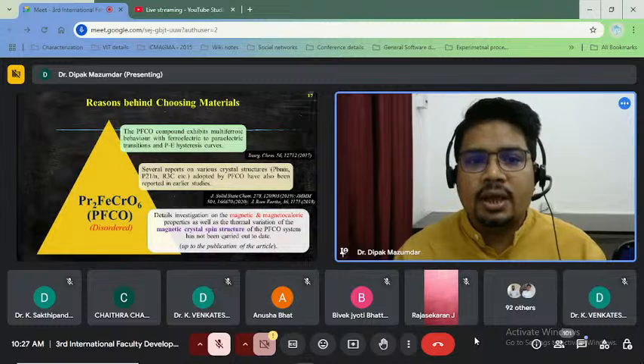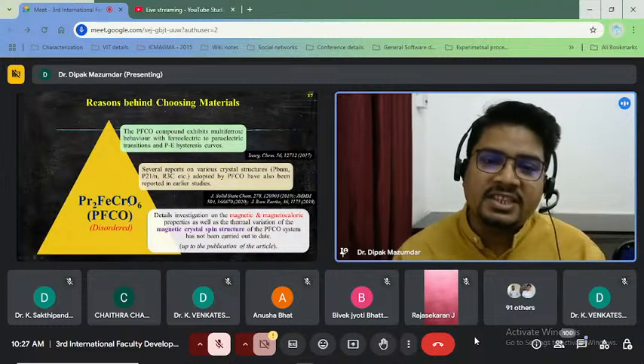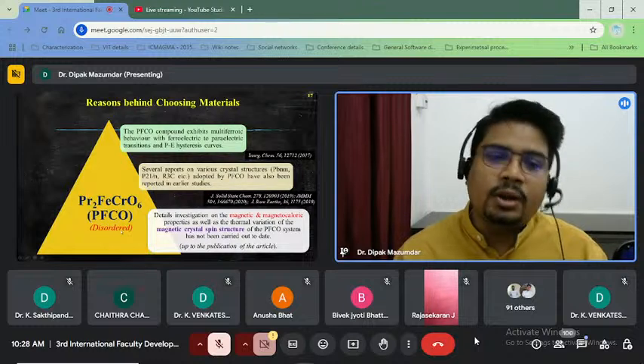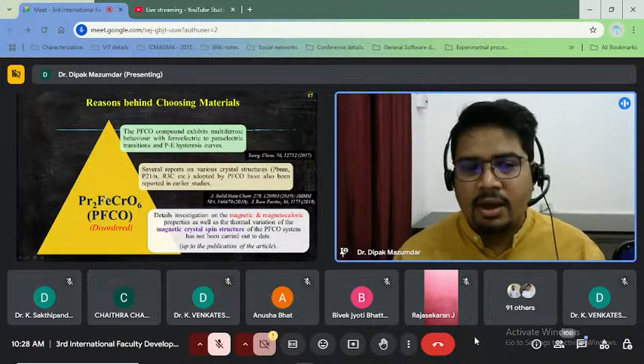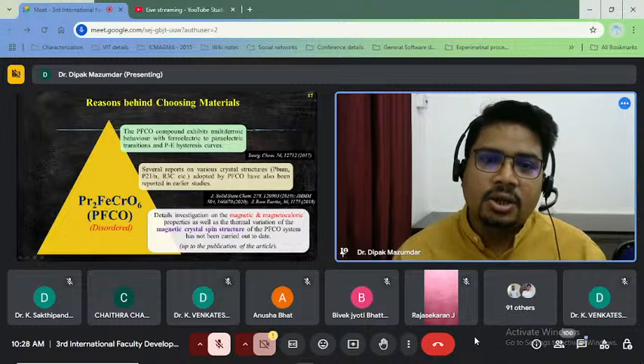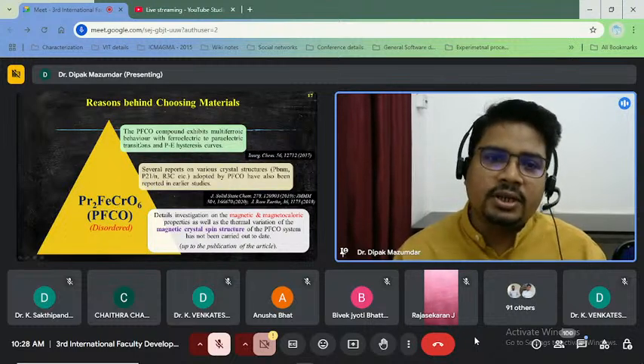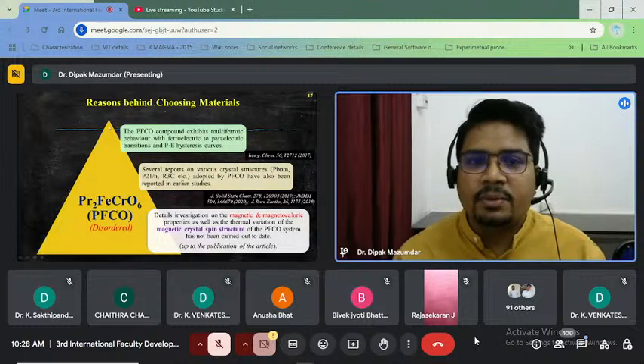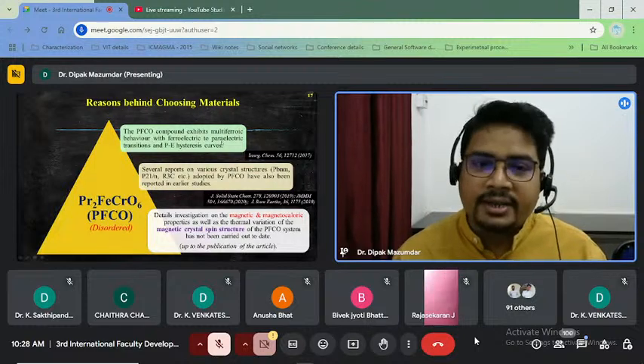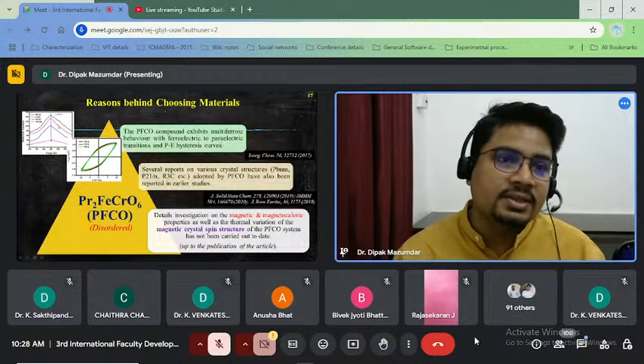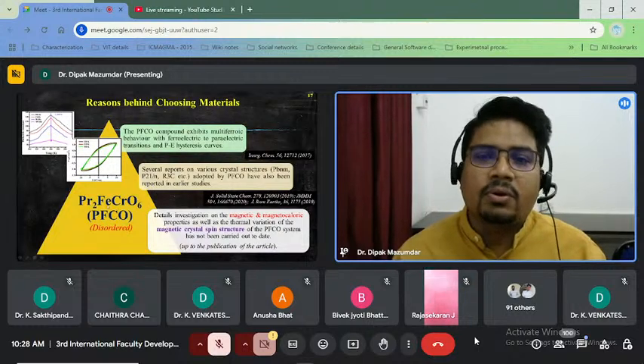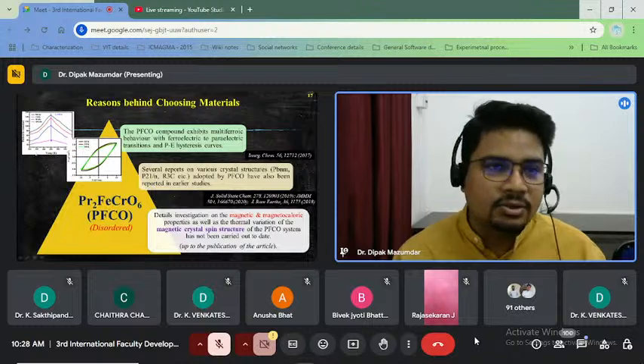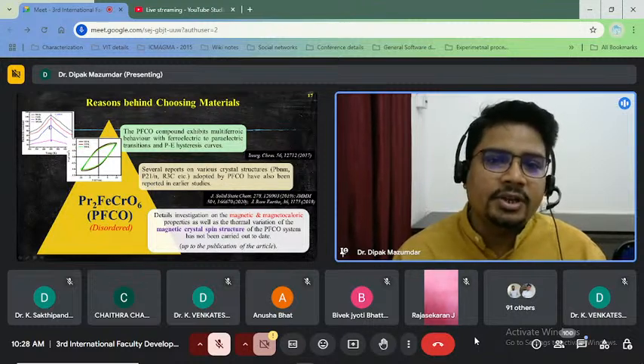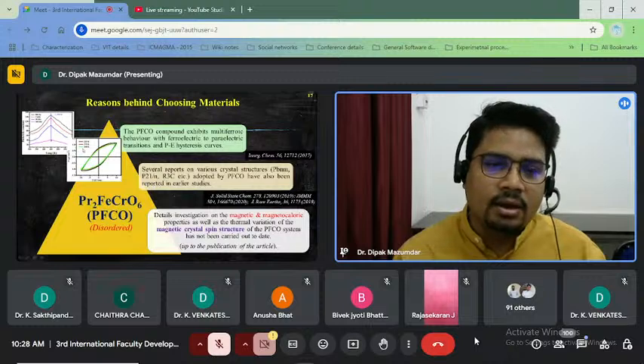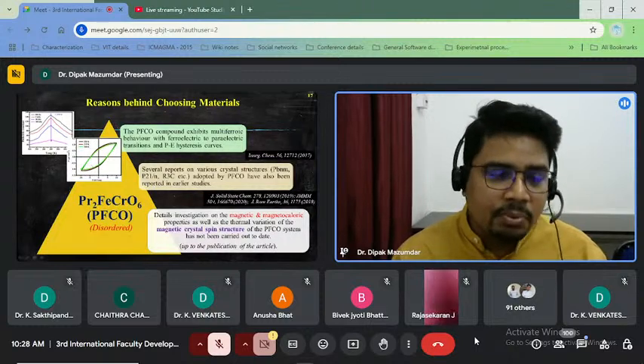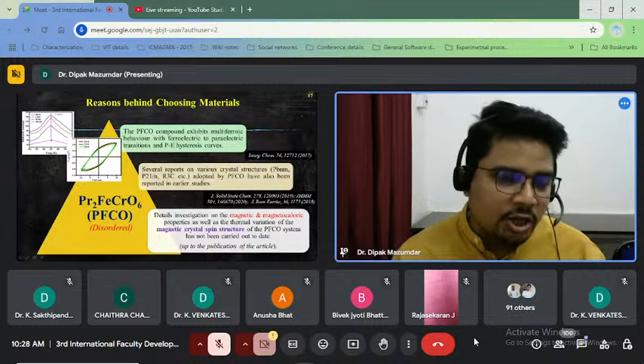And next I have chosen another compound, which is Pr2FeCrO6, PFCO, a disordered double perovskite, because you can see iron and chromium have comparable ionic radii. An earlier report shows that this compound exhibits multiferroic behavior, with a ferroelectric to paraelectric transition and a P-E hysteresis curve, as you can see in these two figures. This is very important from the practical applications point of view.